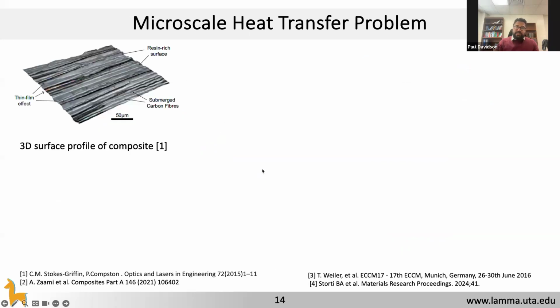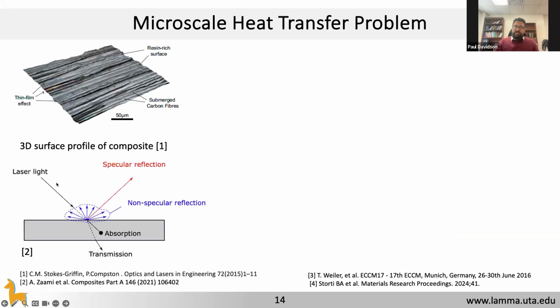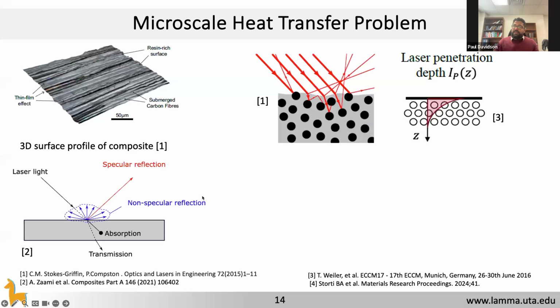So this itself is a complicated process, and this is at macro scale. But if you think about what happens at the micro scale, the surface of the tape is very uneven due to the very nature of it being a heterogeneous structure. And because of this, you have an incident laser light, you have non-specular reflection, specular reflection, some amount of energy is absorbed, and some is transmitted through. And then what is even more interesting in thermoplastics is that for the given incident energy due to laser, specifically here, all these studies are done on laser, the thermoplastic material itself, PEEK or whatever thermoplastic you use, is essentially transparent to the incident radiation. And that is because the radiation absorption of the material is at a much higher wavelength than what you would have for a laser.